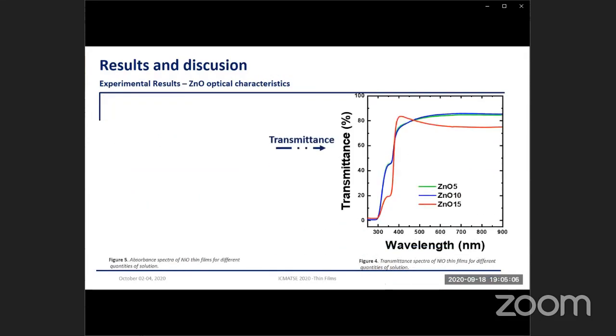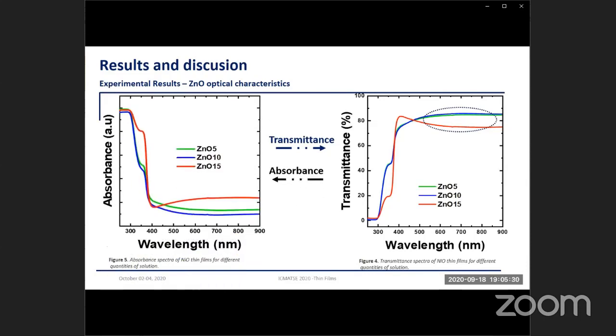Zinc oxide shows high transparency in the visible range too. The average transmission value is over 85% for zinc oxide 5 and zinc oxide 10, approximately equal, and decreases by 9% for zinc oxide 15. The absorption increases in the UV range, which confirms the increase in the thickness. From this optical measurement, we extract the band gap of nickel oxide and zinc oxide.